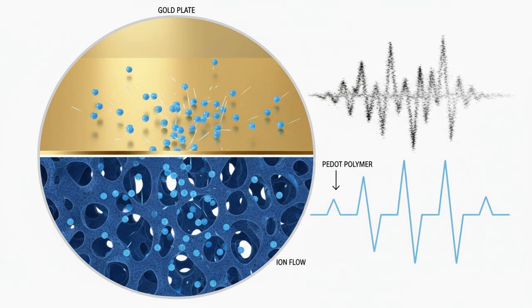Furthermore, they lower the contact barrier. Dry metal electrodes often face high resistance at the skin interface, sometimes hundreds of kiloohms. PEDOT-printed polymers are soft and chemically similar to biological tissue, forming a much more intimate wet contact. This drops impedance, often below 10 kiloohms, without the need for those messy conductive gels that dry out over time.